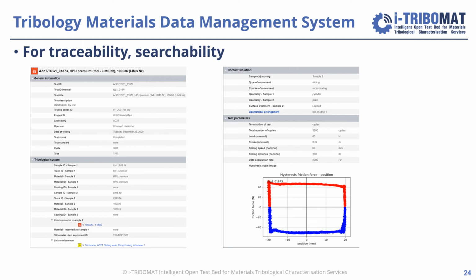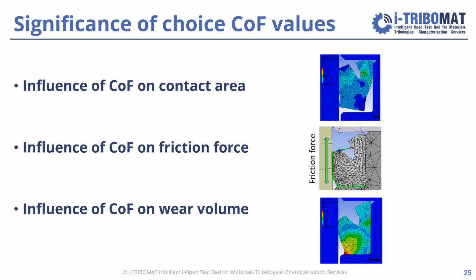And you can even see the quality of the test via this hysteresis curve, which shows the coefficient of friction along the stroke of the back and forth movement. So this allows complete traceability. You can search for different criteria, and you can see the quality of the test and choose which values you actually want to use for your simulation.